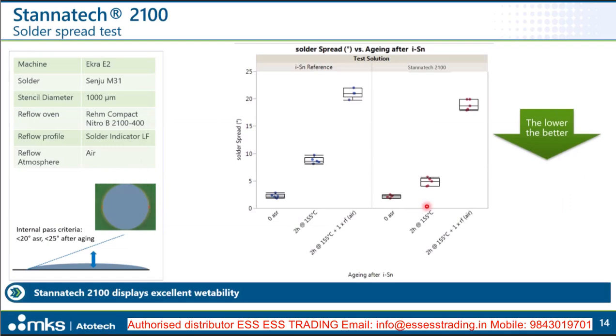I think this is a solder test which is well known. What is done here is that a solder depot is printed on the pad, and then the panel is reflowed in the reflow oven. What we finally measure is the spreading angle of the liquid solder on the surface. We are comparing the immersion tin reference with the Stannatech 2100 for different aging conditions: as received, after thermal aging and after thermal aging plus reflow. What you need to recognize, of course, is that a lower spreading angle indicates better solder spreading, meaning lower values are preferred, and the higher the value, the worse the wetting.